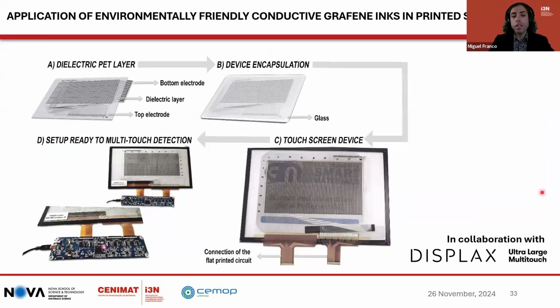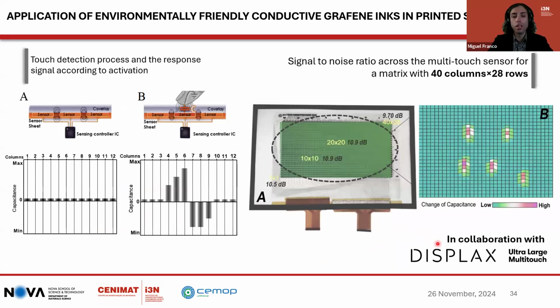In this capacitive sensor, the PET acted as a dielectric layer. The device is encapsulated with glass, followed by the connection of the flat flexible printed circuit. Finally, it is connected to the PCB hardware that detects the multi-touch. This figure represents the touch detection process and the response signal according to its activation. In the presence of a finger, it triggers a local change of capacitance, which can be read by the circuit. The printed capacitive sensor has a signal to noise ratio around 10 for a matrix composed of 40 columns and 28 rows.